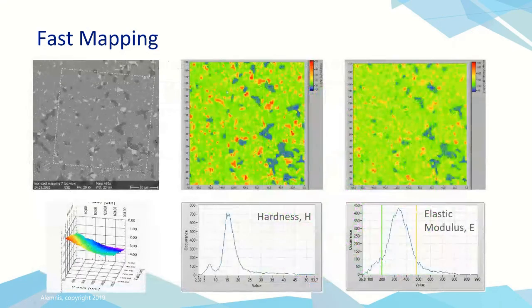So here's the hardness map in the middle, the elastic modulus map to the right. The data can also be shown as histograms. And as we know the point where we touch the sample, we can also plot a topography map in 3D to show the topography of the surface.